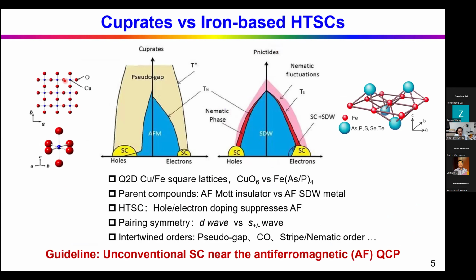So when we look at the structure and the phase diagram of the cuprate and the iron pnictide high TC superconductors, we can find similarities, which may offer us some clues for finding more unconventional superconductors. For example, both families feature a quasi two-dimensional square lattice for the copper and iron cations. And the parent compound has a long-range antiferromagnetic order, and the high TC superconductivity appears when you suppress the long-range antiferromagnetic order by either hole or electron doping or by applying pressure.